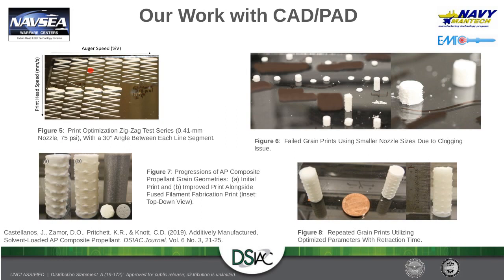In order to generate this optimal printing envelope, as efficiently as our resources allowed us to, we decided to create a small design of experiments in which we observed the 4 parameters that I mentioned before. We essentially created these small zigzag tests that would create line segments, in which each line segment would represent a different print head translation speed, and each zigzag line represented a different auger speed. Then each set of those zigzag lines would represent a different nozzle diameter and pressure as well. That way, we created almost a shotgun approach to determining the optimal regime for these parameters.